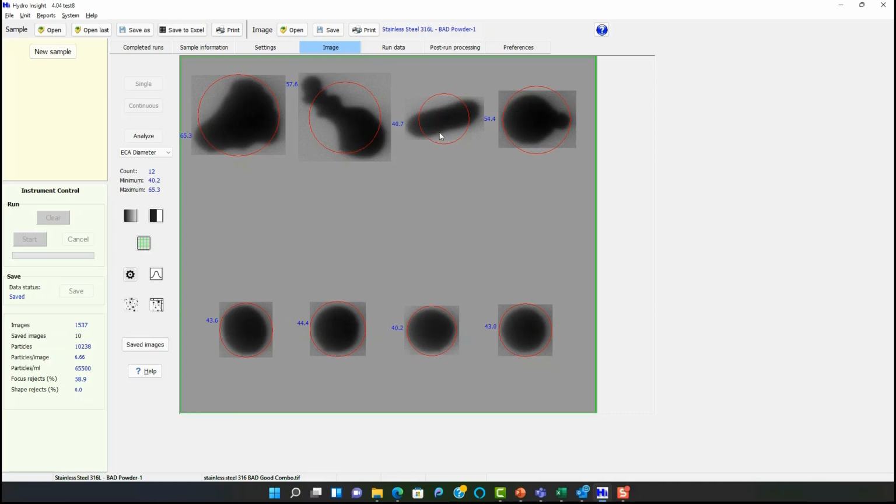In this case, what we really need to do is get a lot more information to complement size and get some shape information. Out of all the different shape parameters, we chose a few. One of them, as we talked about earlier, was equivalent circular perimeter. By having the perimeter, these rough edges, you can really accentuate the differences between a particle that is round and something that has all these different edges to it.